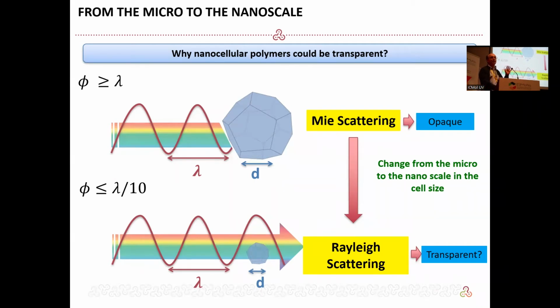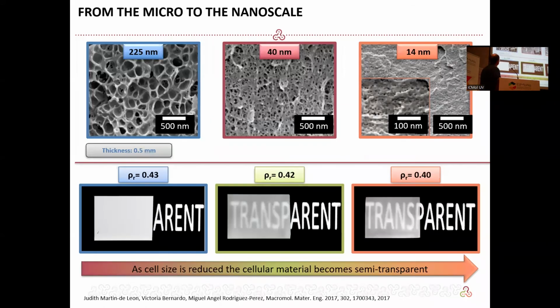Instead, if the cell size is much smaller than the wavelength of light, that's the key concept here. So basically, when the scattering center for the light is 1/10 in size of the wavelength of light, then we move from scattering, the normal one, to Rayleigh scattering. And Rayleigh scattering is a scattering that is much less intense. So if we reduce the cell size to a value of around 50 nanometers, because the wavelength of light on average will be 500 nanometers, so 1/10 is 50, we can make nanocellular polymers that are transparent. Here you have some examples produced in our lab.